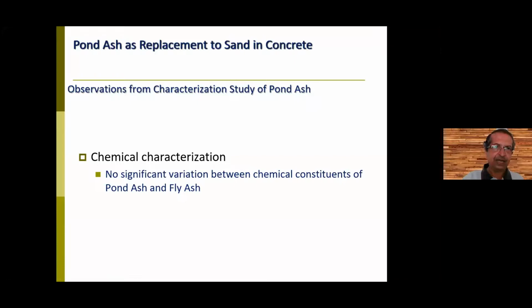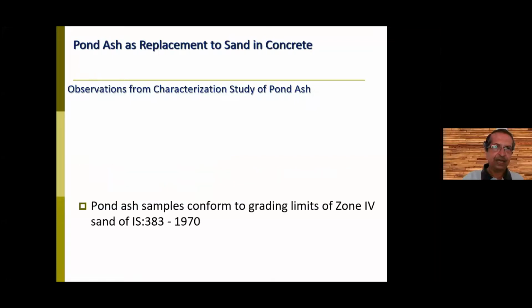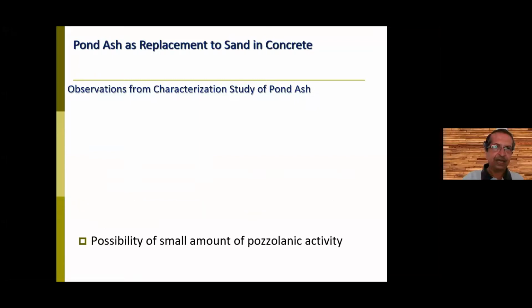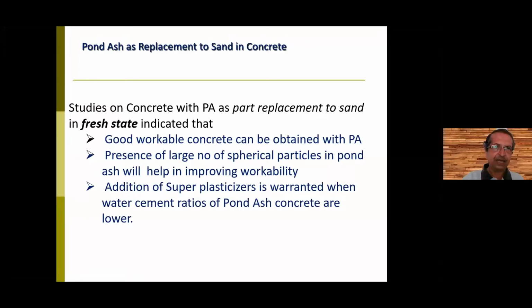Chemical characterization of pond ash indicated that there is no variation between the chemical constituents of pond ash and fly ash, because basically it is the same material. So pond ash samples conform to grade zone 4 of IS 383. At that time it was IS 383-1970 which was being used. So there is a possibility of some pozzolanic activity, and studies were conducted with pond ash as a part replacement to sand. In fresh state, it indicated that good workable concrete can be obtained.